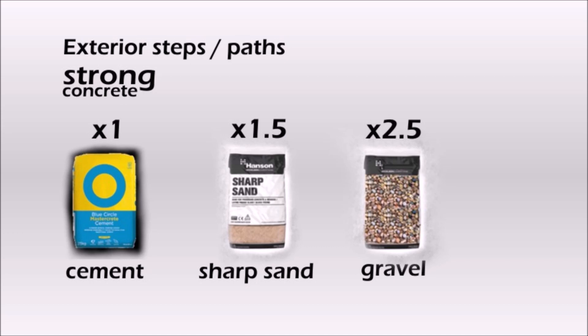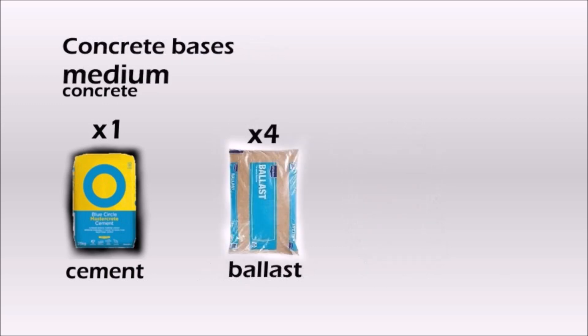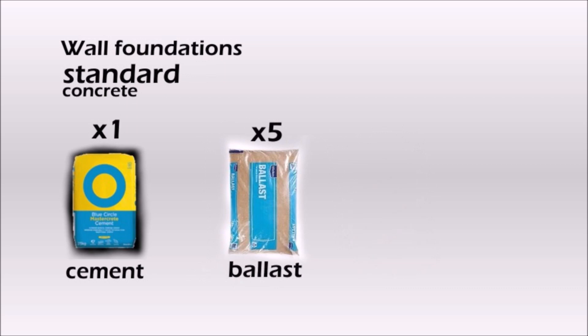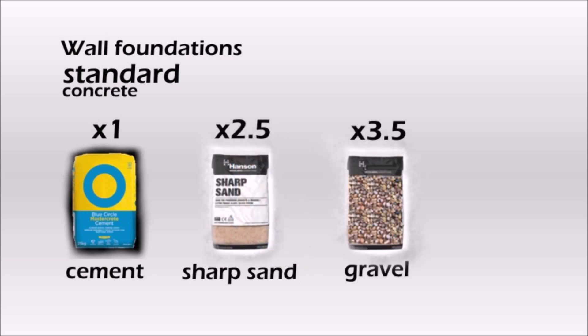Floors or concrete bases need medium concrete: one part cement and four parts ballast, or one part cement, two parts sharp sand, and three parts gravel. Foundations require standard concrete: one part cement and five parts ballast, or one part cement, two and a half parts sharp sand, and three and a half parts gravel.